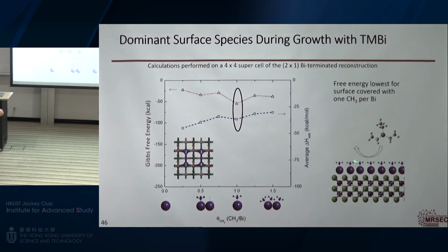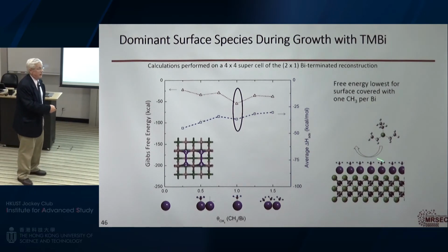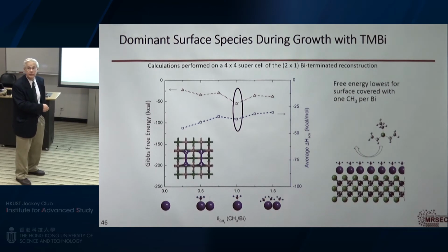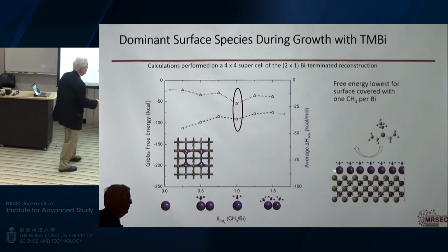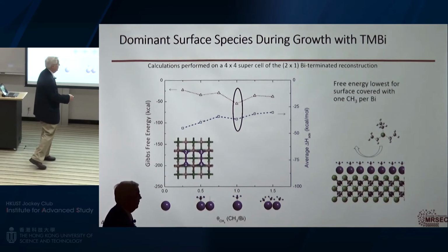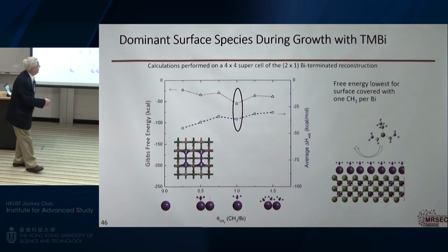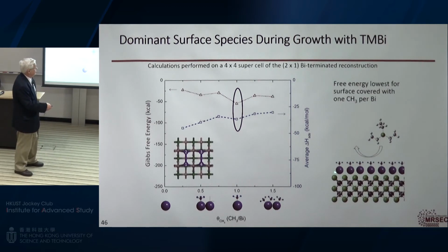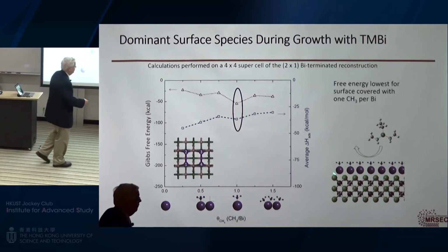And it's the methyl groups on the surface that keep any other reactions from happening. It forms like a Teflon on the surface. And so the rate limiting step is just removing these methyl groups. Now when I'm growing the film, I'm always coming in with trimethyl bismuth, and so it's always replenishing that. When I stop putting trimethyl bismuth in, there's lots of bismuth on the surface, and it starts growing and incorporating again. So the rate limiting step here was the removal of methyl groups.